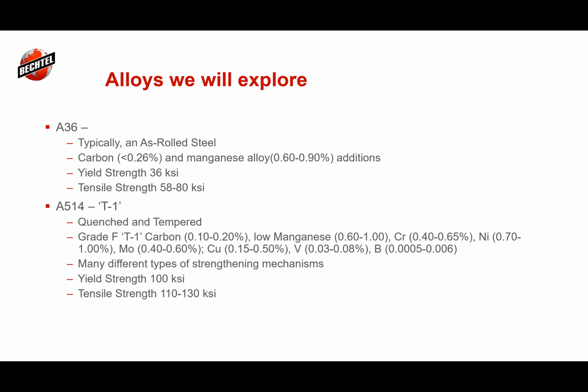Namely alloys that are coming in maybe with higher chemistry than we anticipate, alloying elements that we wouldn't normally see, and that can affect when we take a look at the CMTR. If what we really have is just a low carbon manganese steel, or it's having some trace elements of chrome or nickel in it that could raise the hardenability.